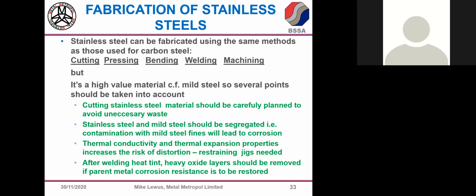Never use those also for stainless steel, because you'll just transfer the more anodic steel, the mild steel or low alloy steel, and it'll contaminate the stainless steel, and that'll just promote points or sites where you get the start of some sort of galvanic corrosion activity.